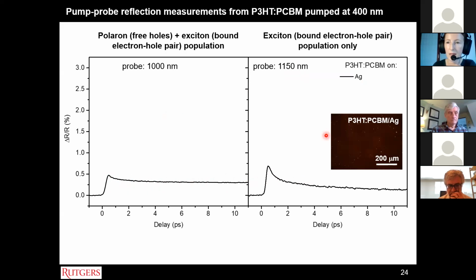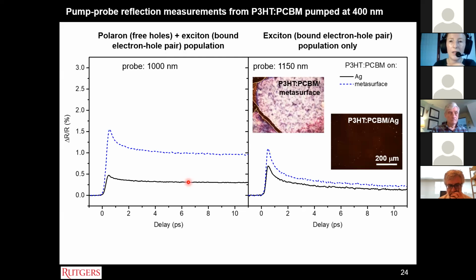And you can see the polaron and exciton population is relatively modest, I would say, for the P3HT on planar silver, and comparing the exciton intensity with the polaron and exciton, the delta R over R value, you can see that they're relatively similar. So the majority of the signal is expected to be from the excitons, although the increase at longer time is from the polarons. You can see when you add the metasurface, there's a strong increase in both the polaron and exciton population, but more so in the polaron population. As you can see from this larger increase here, we're probing both polarons and excitons, but the smaller increase for just the excitons.